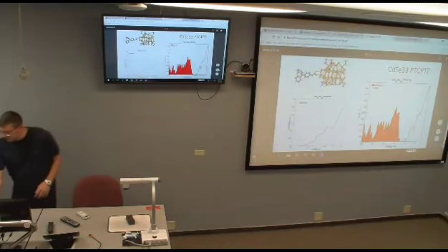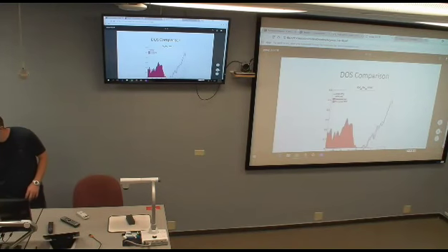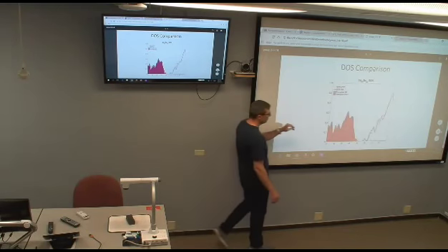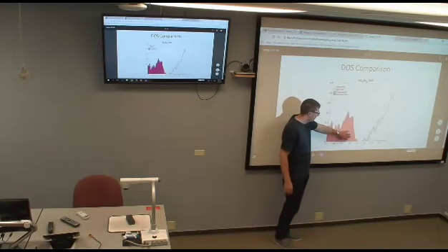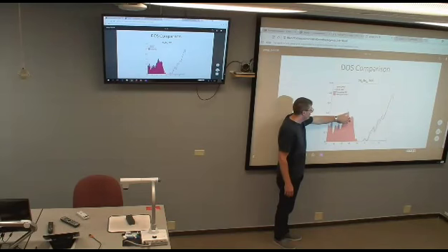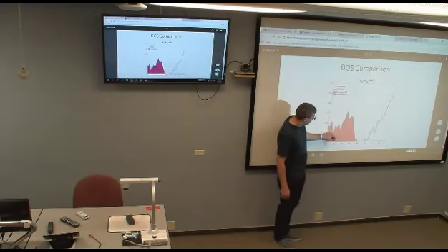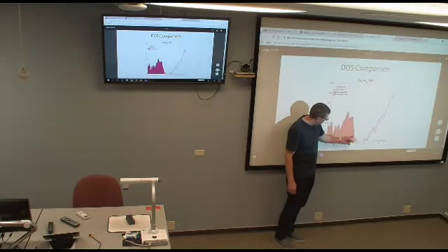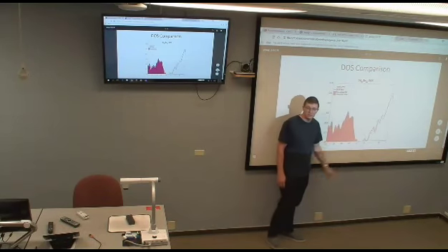And I do have, I'll just jump to this other slide. I'll just show this. So looking at the density of states comparison, the red is for the sulfur linker groups and the blue is for the carboxylic groups, and so you can kind of see this darker line edge here where the carboxylic density of states drops off with an extended density of states for the sulfur groups.